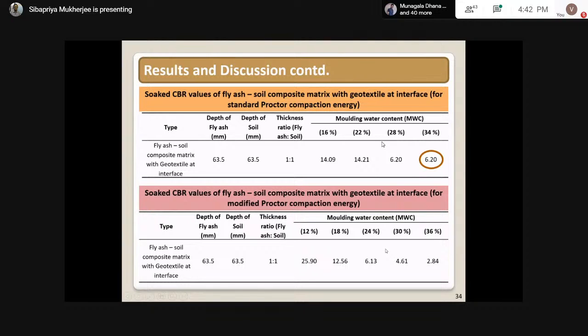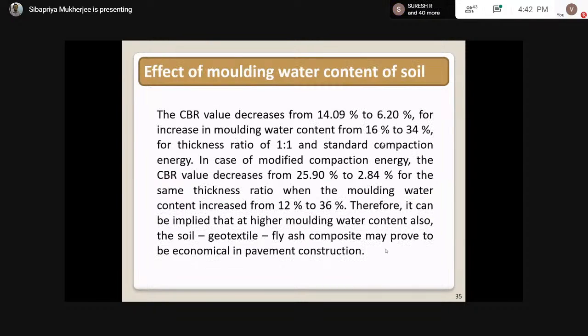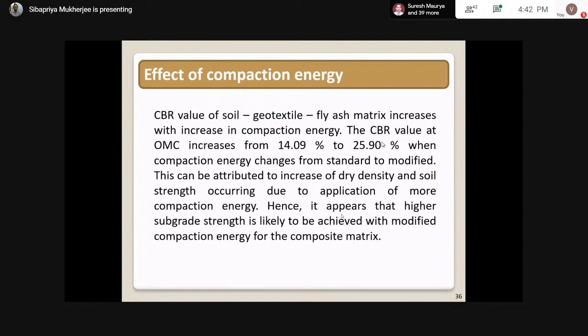Another thing, although it is not presented here in the first study, is that when we go beyond OMC, the CBR is falling, but later we introduced one improvement factor. In the first study that improvement factor becomes less, but here this improvement factor has increased with molding water content. This is the summary of the findings, which I have already told you. It is decreasing from 14.09 to 6.2 for standard Proctor, and 25.9 to 2.84% for modified Proctor of the same thickness ratio, with increase of molding water content from 16 to 34% for standard Proctor and 12 to 36% for modified Proctor. And with compaction energy, the CBR value at OMC increases from 14.09 to 25.9.